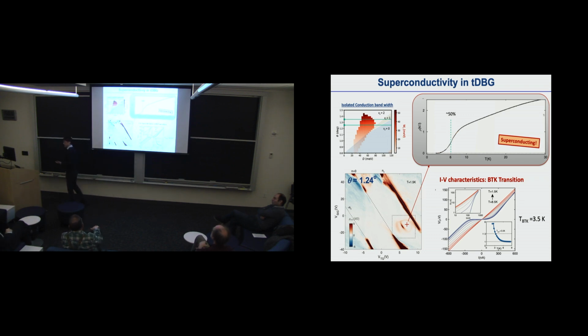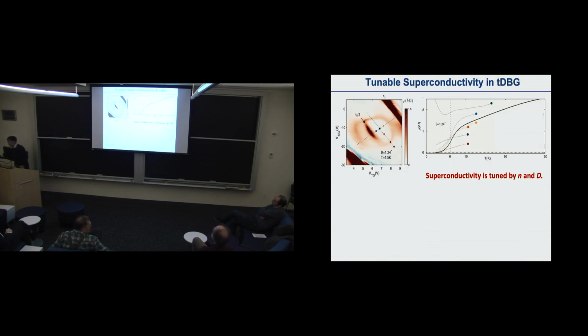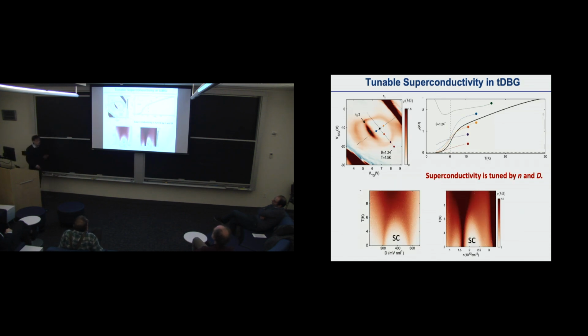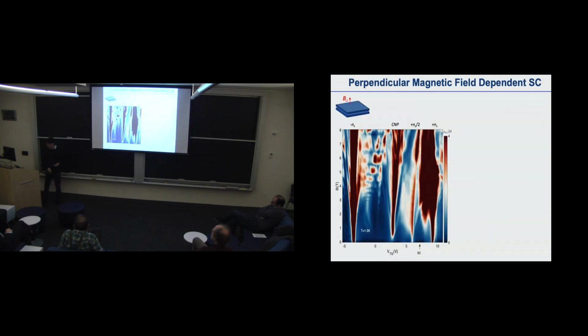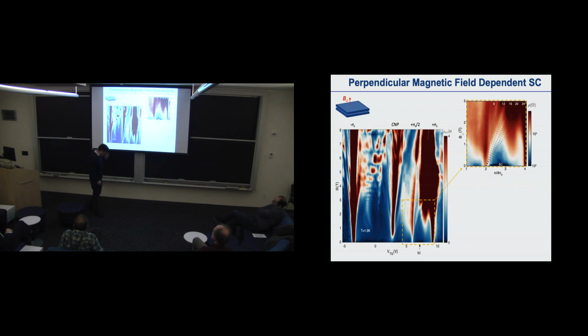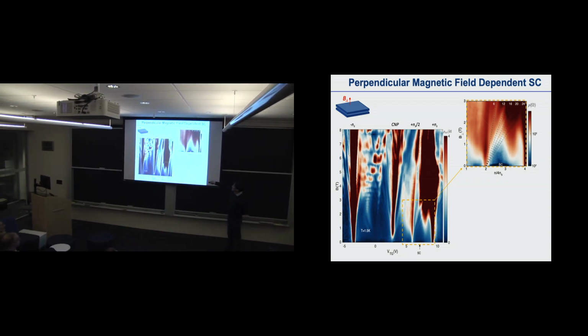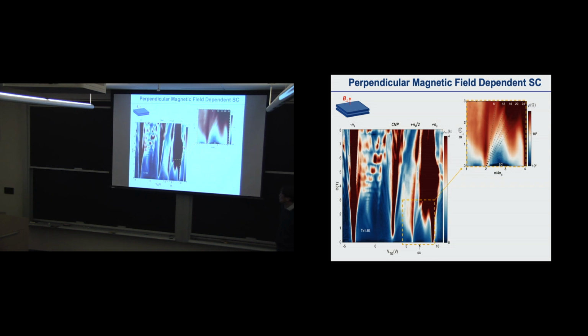This superconducting gap can be controlled by both the electric field and magnetic field, so you have tunable superconductivity in that way. That part is not surprising - when you apply the magnetic field, you of course kill the superconductivity, and once killed, quantum oscillations appear from the band structure. That itself is not surprising.